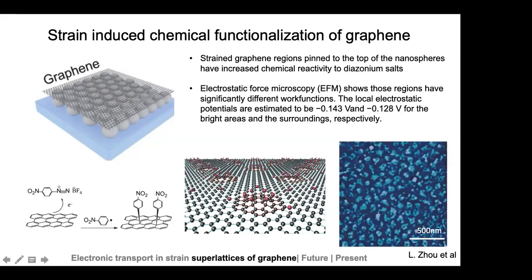They also did electrostatic force microscopy, which shows that those regions which are on top of each of the nanospheres have a very different work function compared to the surrounding material. And hence, the idea is that because of this strain superlattice which is generated in the system, there are chemical properties which are slightly modified. In this talk we will discuss more about the electronic properties of graphene superlattices.